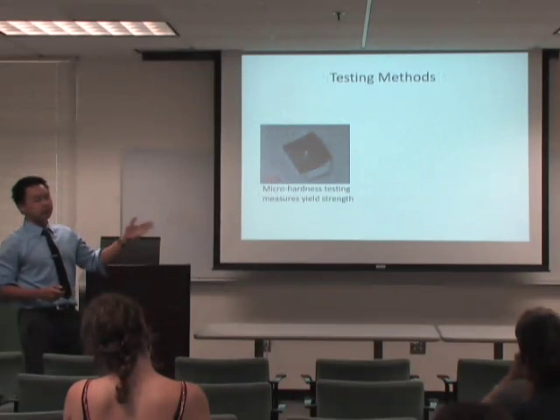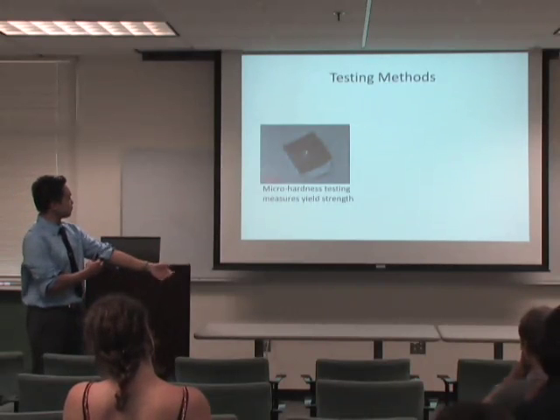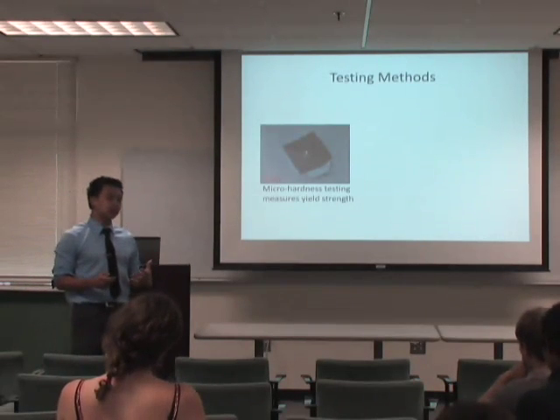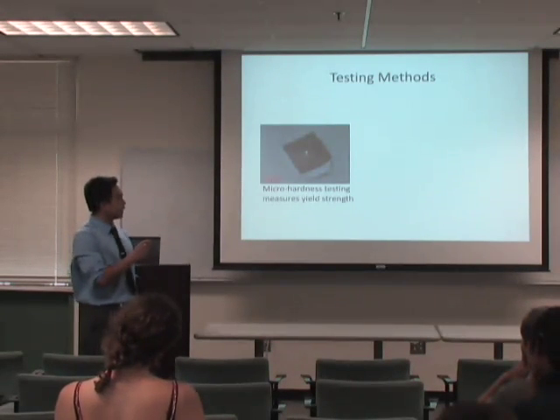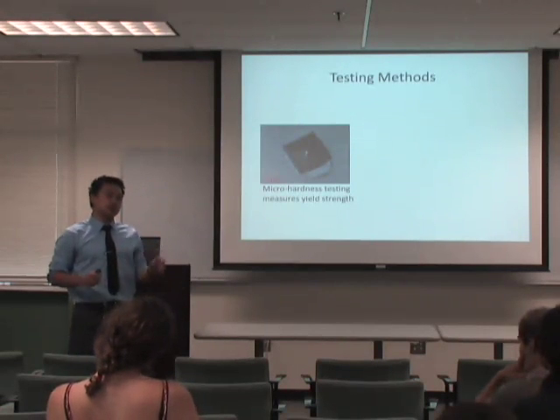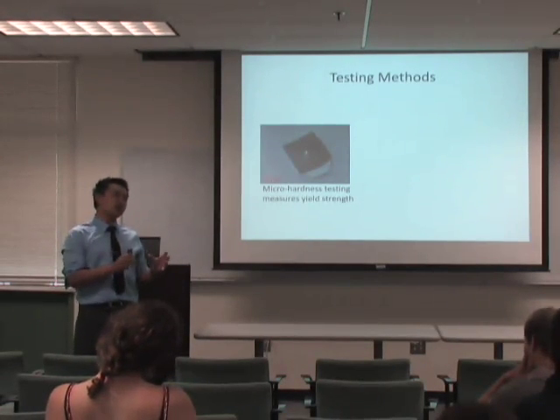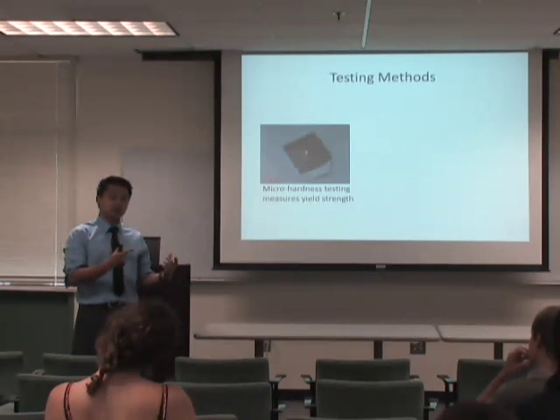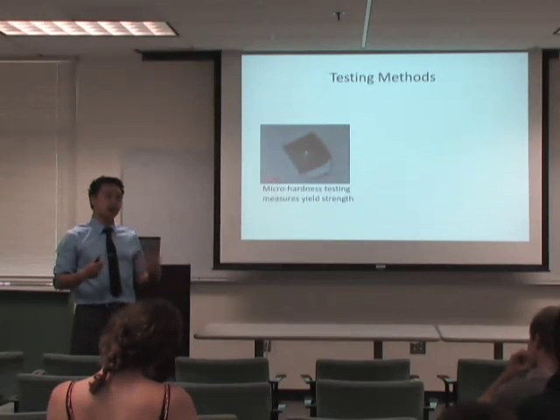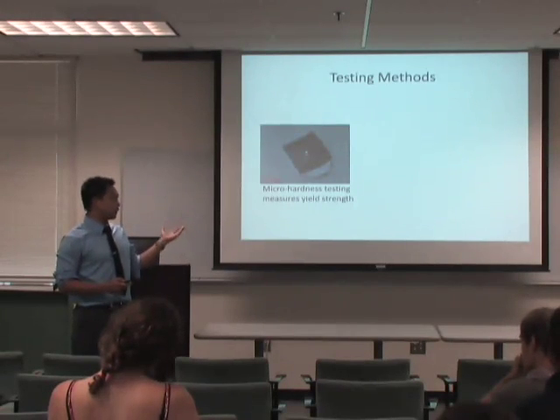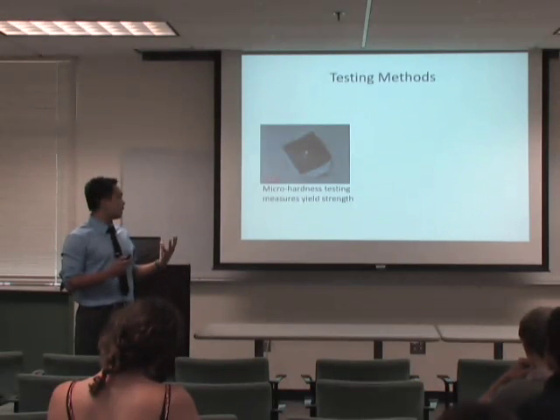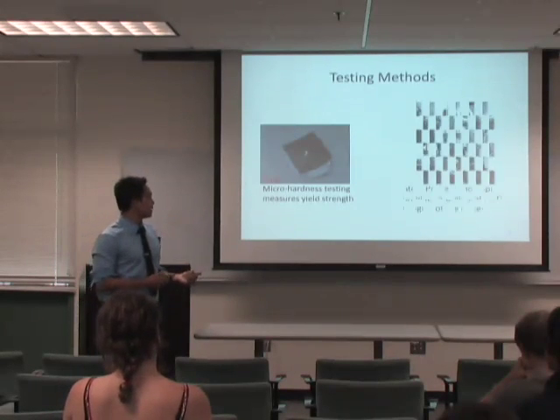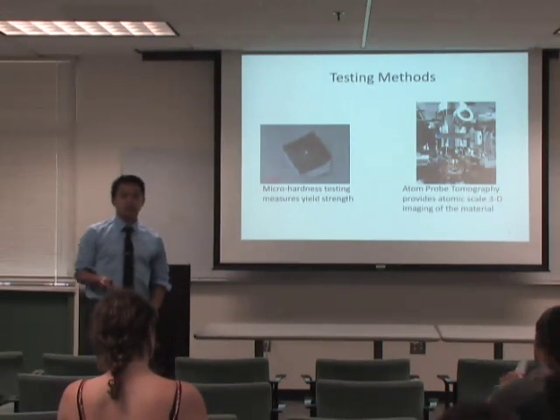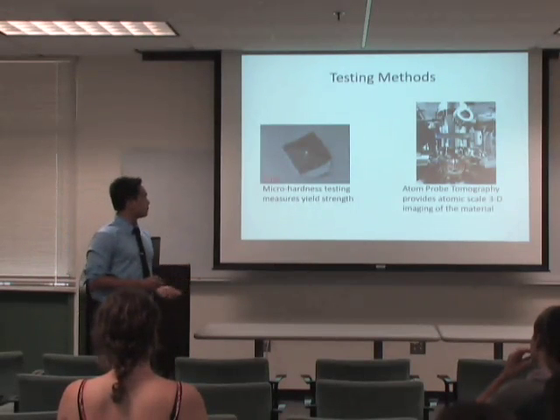Now with the resultant powder and alloy, I've taken hardness on it, which could give me a suggestion of yield strength. And like I mentioned before in the NFA slide, if I do have nano features in my material, which would impede dislocation, I would have a high yield strength. So by judging from the hardness, I can get a guess of whether I had produced nano features or not. And after, I would look at it under an atom probe, which would give me an atomic scale 3D view of my material.